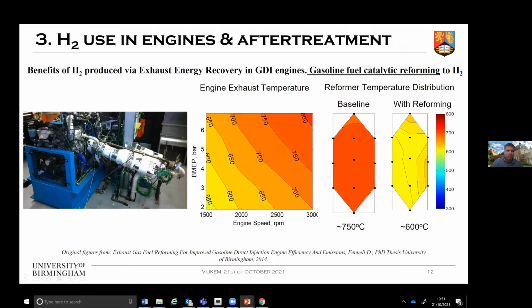So at the university, we had an engine coupled, from a research project, with a three-way catalyst followed by fuel reformers. First, we tried to explore in our engine how much temperature could arrive in the exhaust, to see if the temperature would be enough or not to drive the endothermic reactions. And then we could see how, taking a plate of the catalyst without reforming, the temperature was around 750 degrees. Then we injected a fuel, and then the temperature suddenly reduced to around 600 degrees.